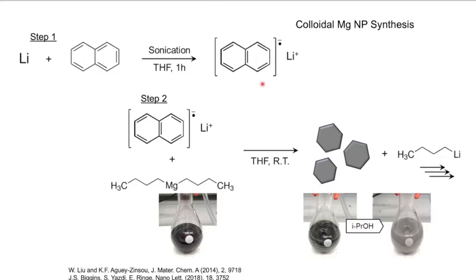It's not that hard. Basically, you need to find something that really wants to get rid of an electron. So a lithium naphthalenide, for instance, will give an electron to a magnesium organometallic precursor. Well, in fact, it will give two electrons and form magnesium zero, a metal that will then form a nanoparticle that will grow into some shape.